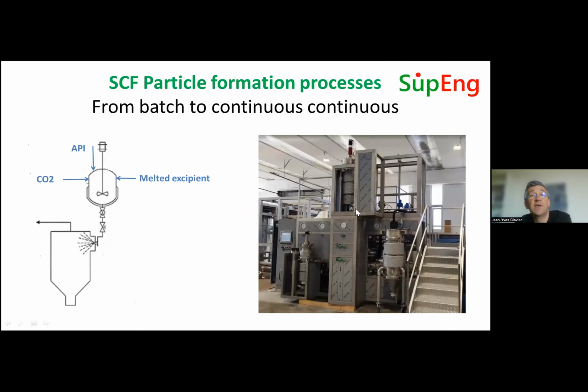So this is why we developed it at large scale, trying to make it continuous and introducing continuously exactly what we want to have at the exit, with controlled flow of CO2, controlled flow of the melted excipient, using it at high temperature, but basically the mix is done at lower temperature, and introducing the active principle to be protected continuously or almost continuously. So we introduce the three of them independently and continuously. We mix them and we spray them continuously. And going through a continuous mode allowed to obtain a process that is much more robust and much better controlled for this very attractive process of particle formation.